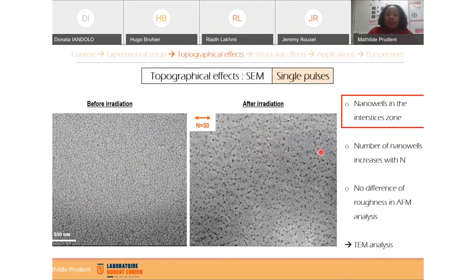After the realization of an AFM analysis, we didn't see any difference between the sample before irradiation and after irradiation, just some small nanometers of difference, but this difference is not significant. For these reasons, we choose to realize some TEM analysis in order to know much more information about the nanowells and their characteristics.